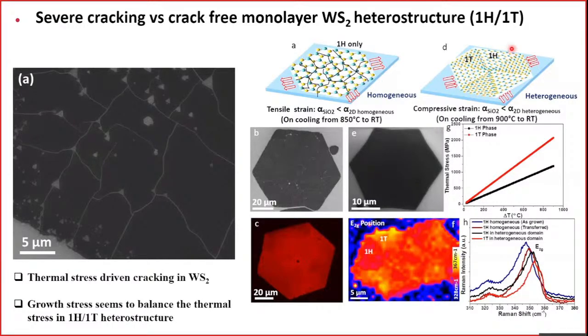How do you know that? We know that by looking at the Raman spectroscopy, where there is a consistent shift. Because of the inbuilt compressive strain, when there is a thermal mismatch, typically you need a tensile stress in order to induce the cracking and fracture. When there is a thermal mismatch tensile stress, the inbuilt compressive stress in this case essentially balances it. That is what stabilizes the heterostructures compared to the homogeneous 1H structure.